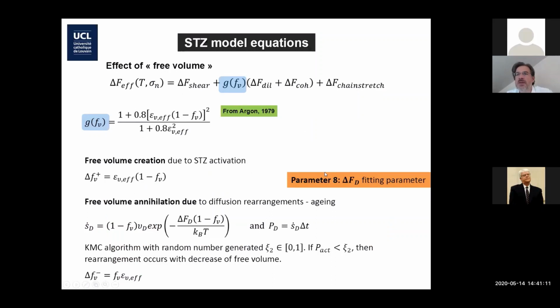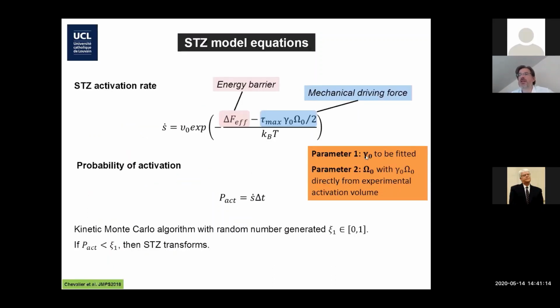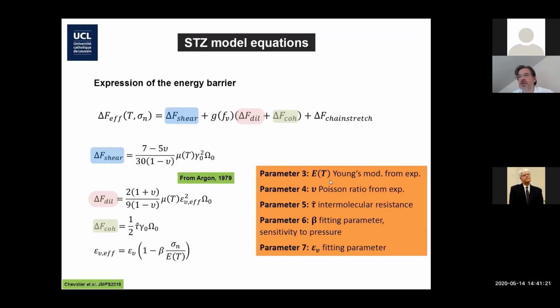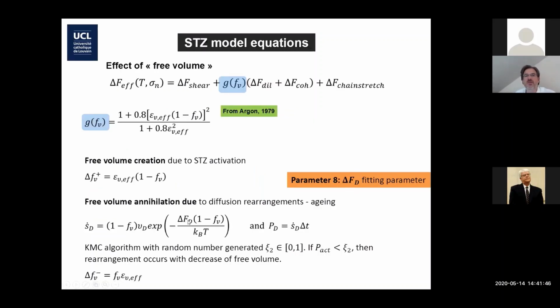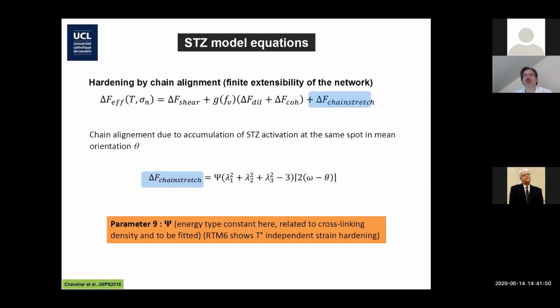By the way, there are 9 parameters: a shear transformation strain, an activation volume that we can measure experimentally, Young's modulus we can measure, Poisson ratio we can measure, and the intermolecular resistance. It has a physical meaning, but basically you will need to adjust this value. Then a fitting parameter taking into account pressure effect, a fitting parameter connected to the dilatation occurring during a transformation, a fitting parameter related to the annihilation of free volume, but that's not very important, and a parameter to adjust for the chain alignment. So 9 parameters, 3 or 4 of them can be obtained directly from direct measurements.